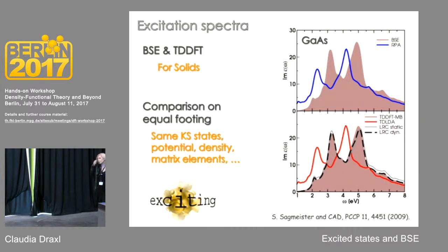You see, for solids, it doesn't do this. So there's no single kernel that would open up the gap, and that's why it's recommended to do a GW calculation and let the kernel only take care of electron-hole interaction. And there are a few kernels here. This is a static long-range kernel, a long-range dynamical kernel. There is the many-body kernel or Nanoquanta kernel, which all give very similar results, but just for this material.